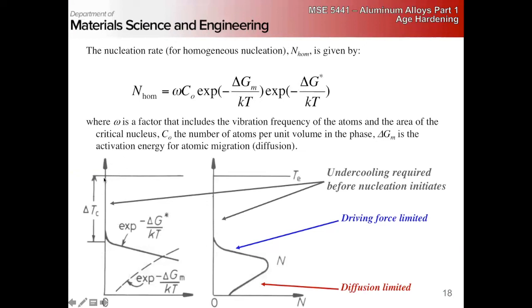So if we look at this, here's our equilibrium temperature. If we're very close to this equilibrium temperature, right, at a higher temperature, diffusion is easier, but we don't have a lot of driving force to overcome our activation barrier, right? We're really close to the equilibrium. As we cool down, this term grows, right? The farther away we get from the equilibrium temperature, the larger the undercooling, the more driving force for this nucleation there is. But at the same time, at lower temperatures, the energy we have available for diffusion, our diffusion rates and our atomic migration rates decrease.